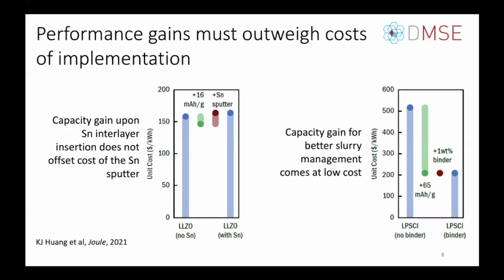And that is a comparison to the right-hand side, where this is a different chemistry, obviously, but the strategy here was an optimization of the slurry chemistry and an addition of more binder that saw a significant increase in performance, as shown by the green directionality there, at not so much added system cost, when we think about that in the context of the model. So in this case, we would see that potentially that strategy, the optimization of slurry chemistry, if we can see these sorts of performance gains, may be a more cost-effective strategy. So again, not to say that this is a strategy to be endorsed, but just this demonstration of these tools to try to inform manufacturing costs at scale was what I wanted to share with you all here.